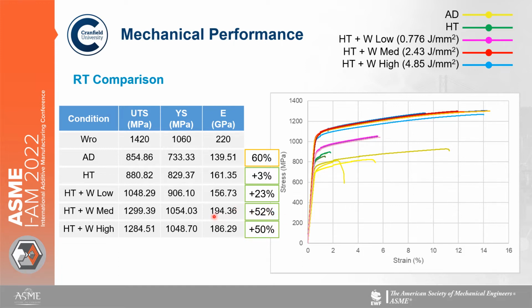What you can see though is that yield stress for our medium speed is very close to our wrought performance, which is good to see. What you also see as well is that elastic modulus is also approaching the wrought material as well.